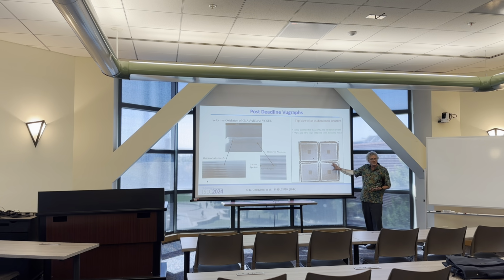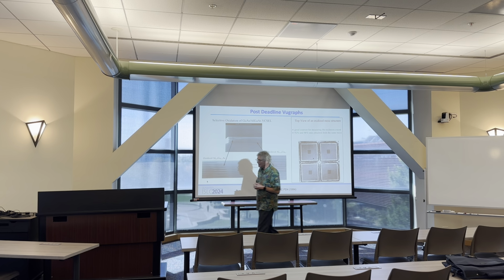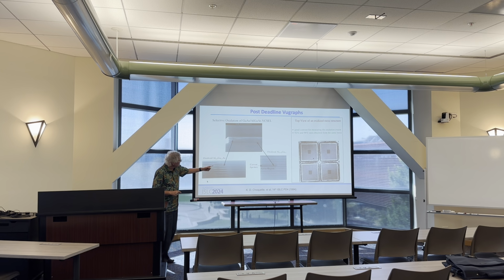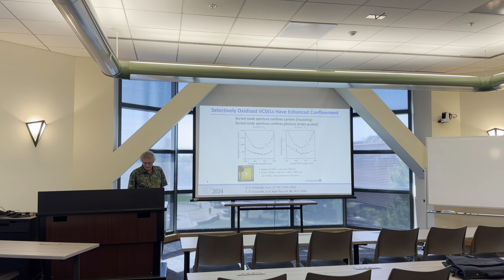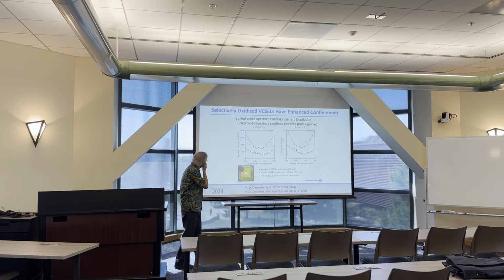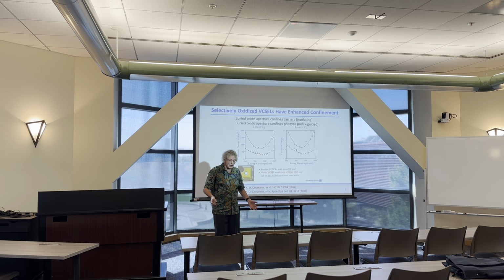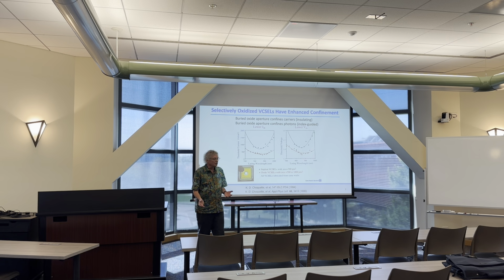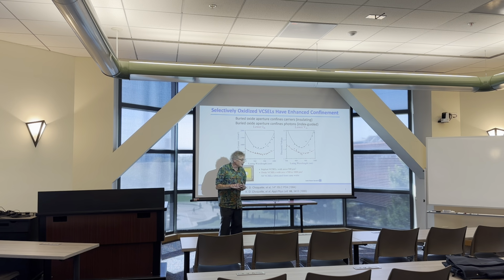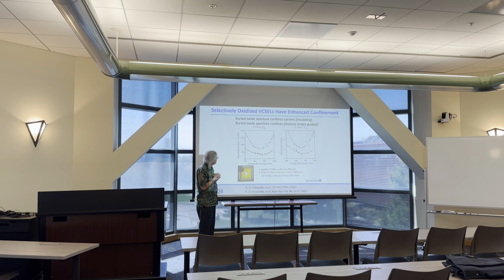When I left Sandia, I couldn't reproduce this until about 2 or 3 years ago. I learned that the camera was really the key part of this. But this is where you can actually see these apertures. Again, this was colorized, but the data that I showed was at the time, the technology that was being used was ion implantation. That basically renders the semiconductor non-conductive. You can confine the current, but it does nothing for the photons.